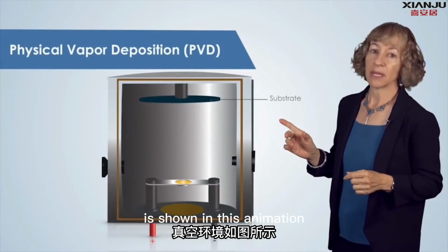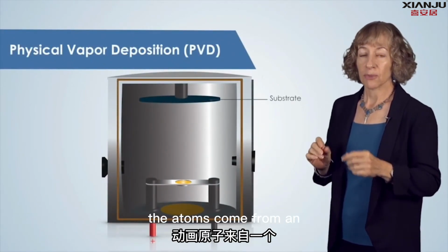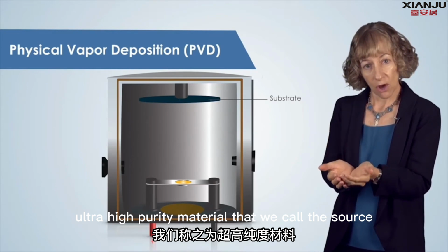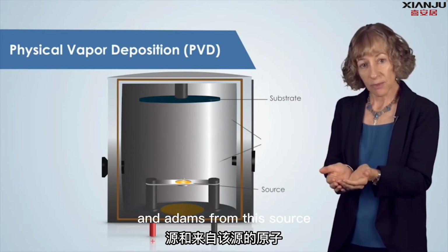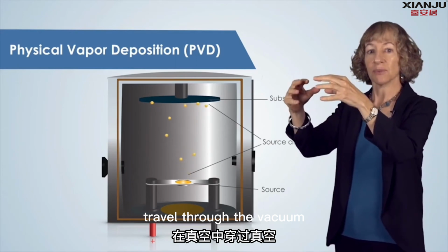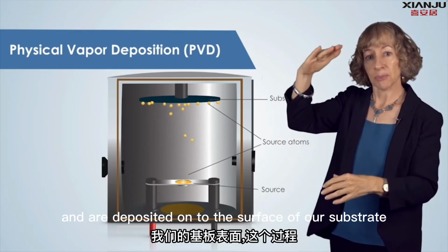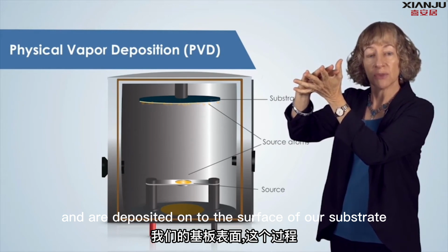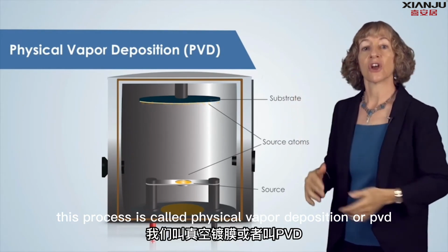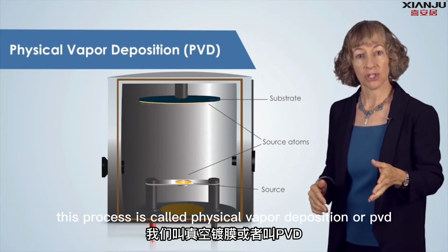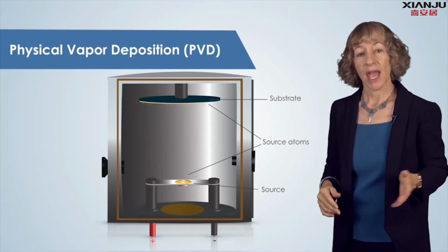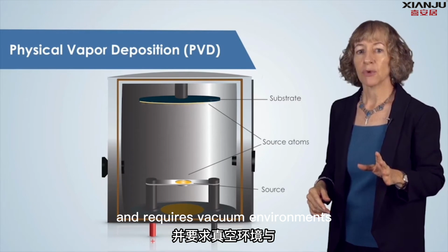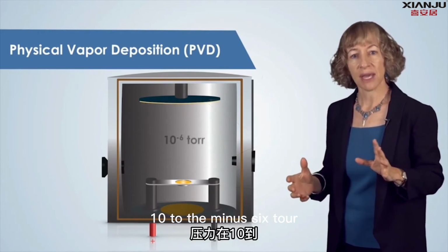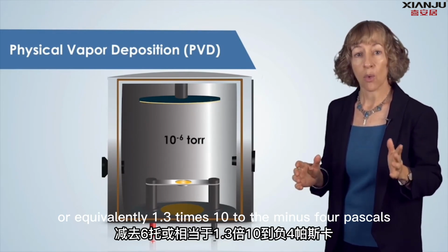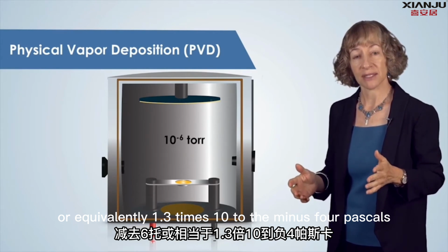high vacuum environment. As shown in this animation, the atoms come from an ultra-high purity material that we call the source, and atoms from this source travel through the vacuum in the vacuum chamber and are deposited onto the surface of our substrate. This process is called physical vapor deposition, or PVD, and requires vacuum environments with pressures on the order of 10 to the minus 6 torr, or equivalently 1.3 times 10 to the minus 4 pascals.